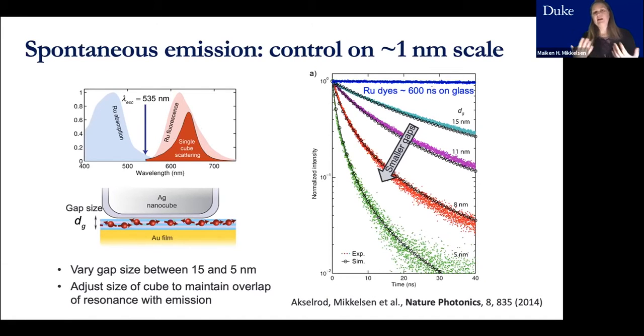And what we are seeing is large modifications in the fluorescence lifetime. So that's what you see here. These measurements are done by exciting the structure with a pulsed laser, and then using time-correlated single photon counting to time-tag the arrival of the photons, which is what you're seeing here. Fitting this can then give you the excited state fluorescence lifetime. And we see that there's a large difference going from a 15 nanometer gap down to a 5 nanometer gap.